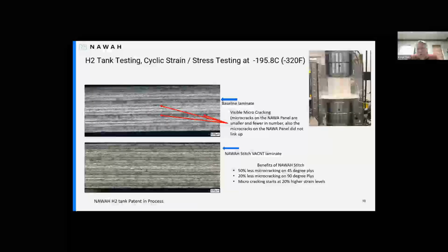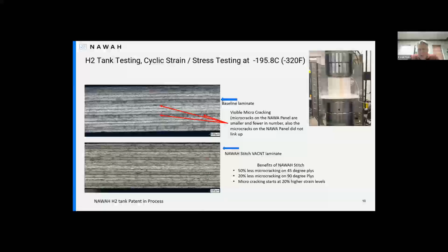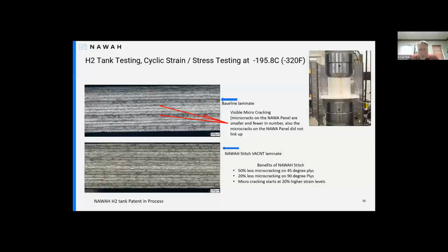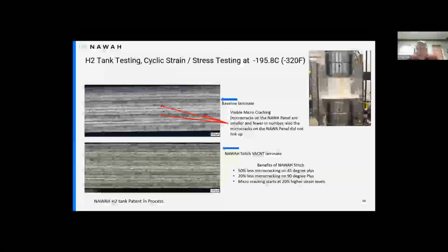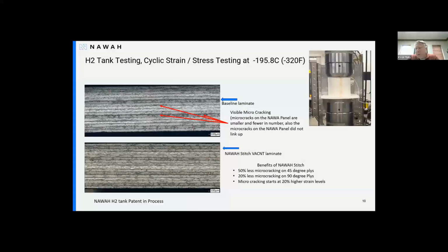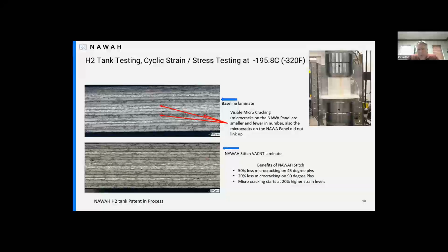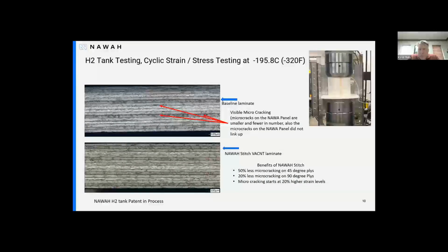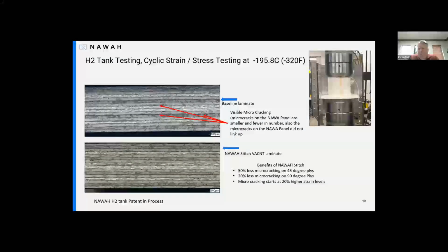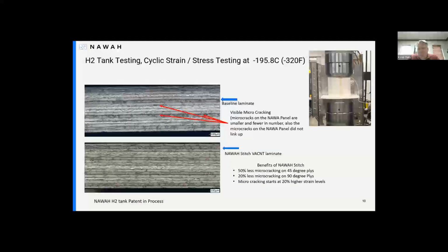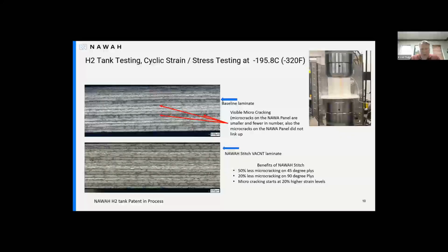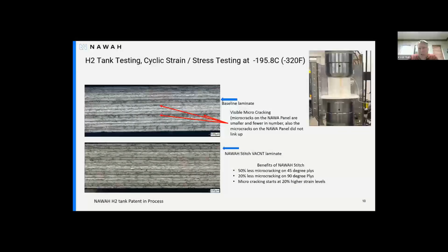We've done testing all the way down to negative 320, and we've done elevated temperature testing. The presenter before showed oxidation. You've got to keep that in mind. So there are limitations on the vertically aligned carbon nanotubes, as there are with any material. But at negative 320 degrees, we showed that we greatly reduced the amount of microcracking, and that the microcracks didn't link up, which helps with permeability. And they were 20% higher on the strain level before they even started. That then gives the design engineer an area where he can actually start to think about designing things like cryo tanks, high pressure tanks, where they're not getting the microcracking.